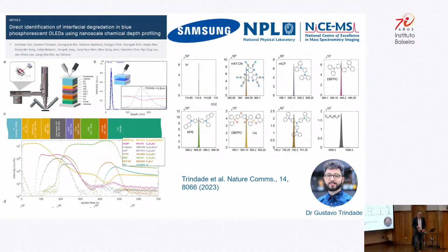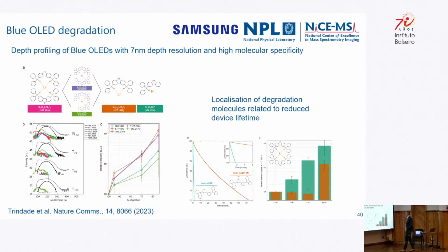Very incredible level of information. And the resolution that we get is very high, so we have the ability to accurately identify what the chemistry is and very accurately localize where that chemistry is. And because of that, we could identify, as we start to age the device, this is a fresh device, there's a 5% aging, 30% aging. We could start then to see the evolution of certain molecules. These are attomole levels of concentration, but because our technique was so sensitive, we could identify what they were. We could see how they correlated with increasing degradation of the device.